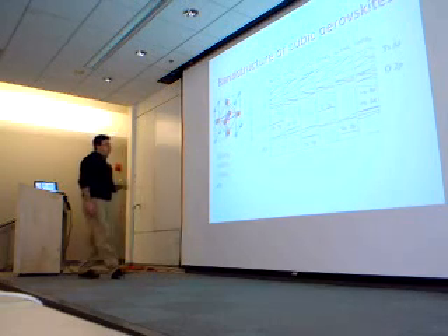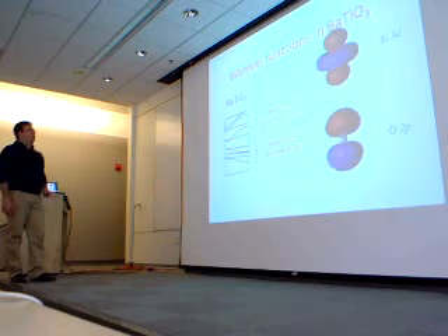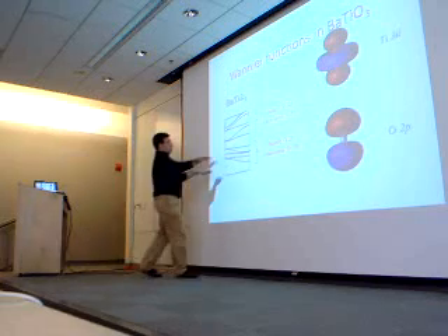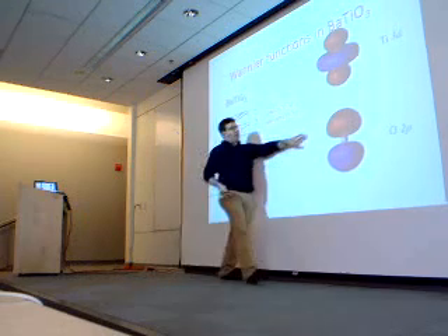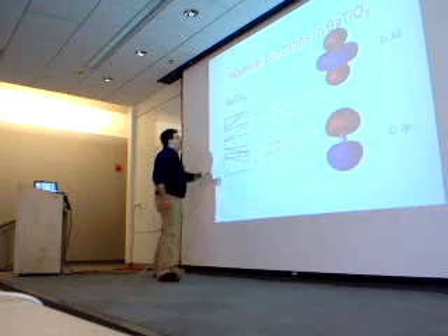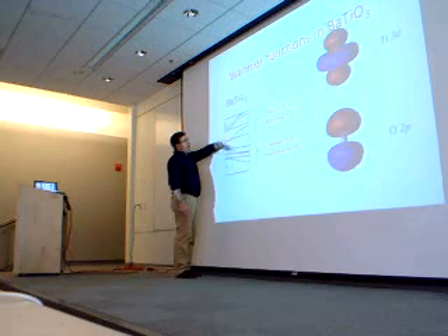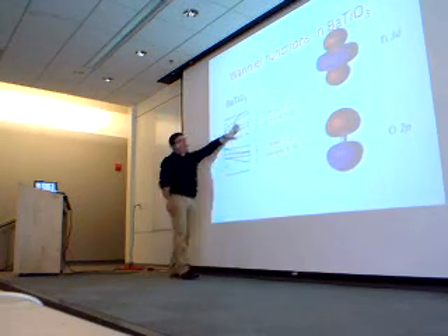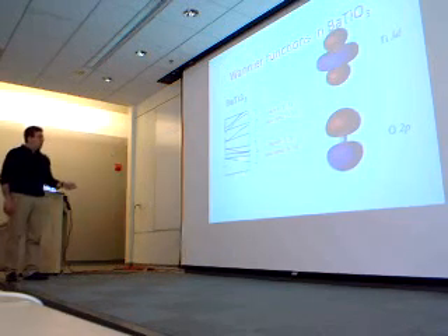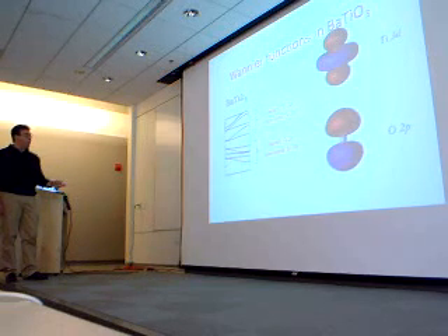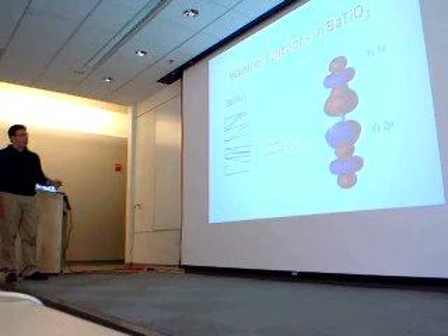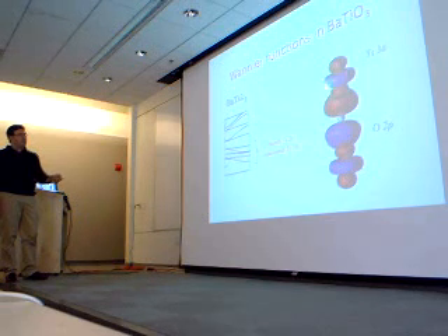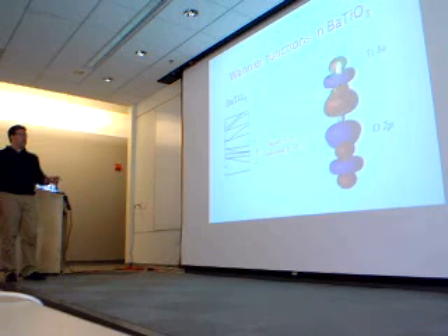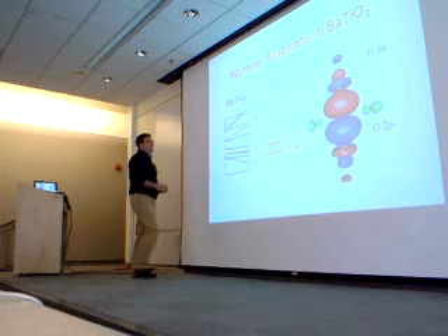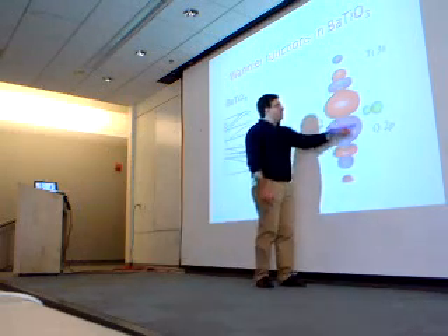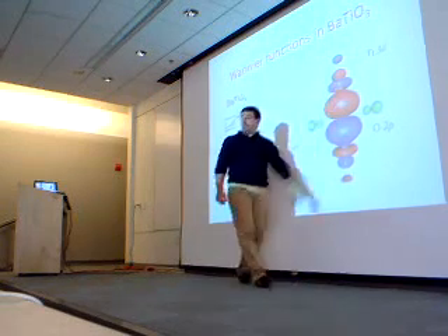But if we look at the Wannier function of these 9 bands, you'll see that they don't actually look exactly as p electrons should look, and this is the reason. So these are the top 9 valence bands, and you could say, well, they should really be looking like pz electrons, but it turns out, even if there is a gap, that they have hybridized significantly with the titanium 3d states that sit here at the bottom of the conduction band. And so when you do the valence wave function for this manifold, you get something that looks a lot like an oxygen 2p with significant hybridization with the titanium 3d. And there is, for the pz orbital, a titanium 3d symmetrically above and symmetrically below. So you'll see the Wannier functions actually looking exactly like this. They look like pz orbitals, but with a very strong titanium 3d hybridization.